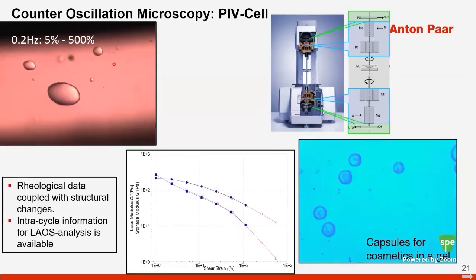Now you can also do large amplitude oscillatory shear type experiments to collect what is happening rheologically, and we have access to intracycle information as well if you want to do detailed LAOS analysis. Here again both motors are oscillating in this counter oscillation type mode, where you can clearly see we can apply strains and understand how the properties are changing as you increase the strain of your oscillation at a fixed frequency.